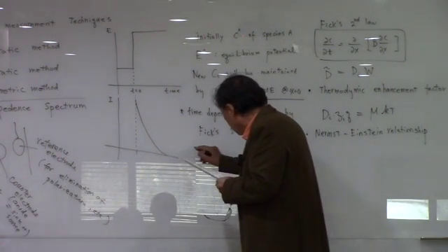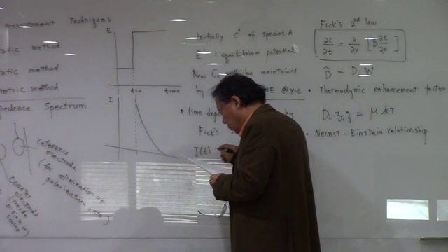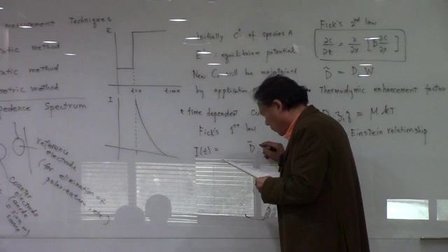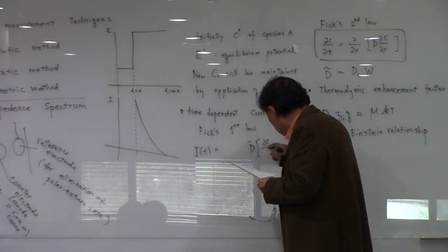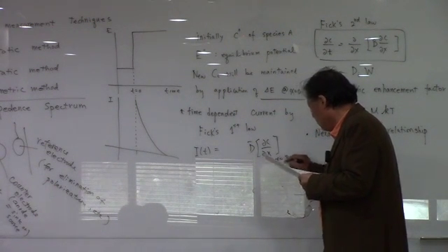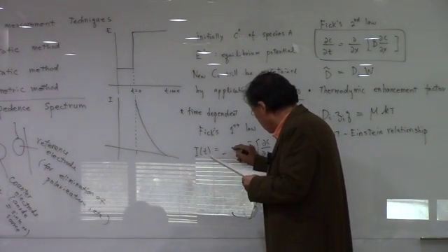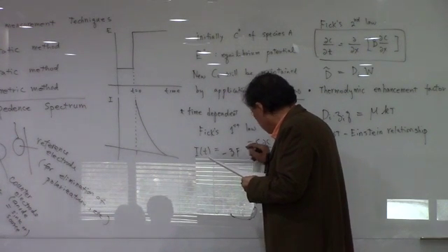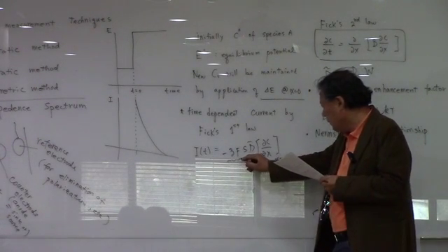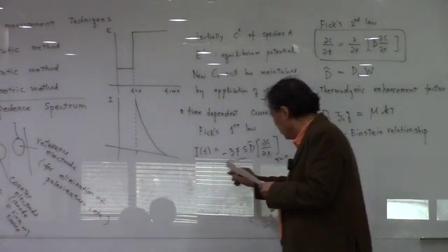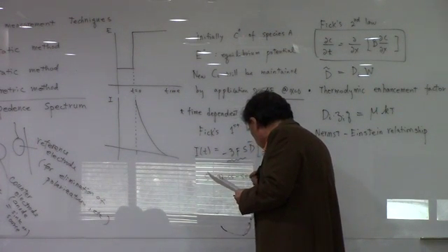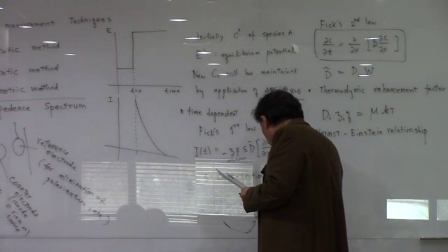All right. The I(t) now should be related to the flux that has flown by concentration gradient at x equal to 0, and then the current is going to be related with these parameters here, and S is the cross-sectional area.